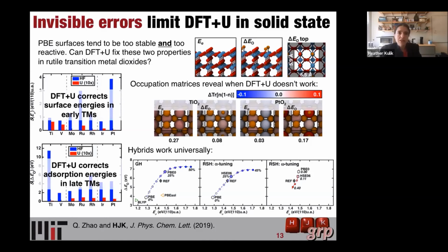I think the challenge is when the two properties you mentioned are additive. So I will get back to your first question in a moment. The properties are additive. So if you change the lattice parameter because you use a U and that U is too big for the lattice parameter, then the band gap evaluated at that overly expanded cell can be wrong because also the structure is wrong. So we know that using a lower U for structure is usually good because of these challenges of over penalizing hybridization in the bond.